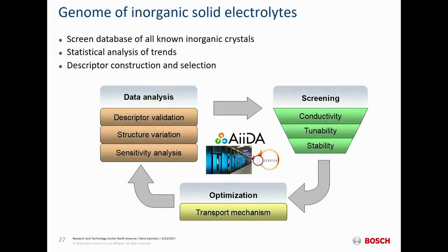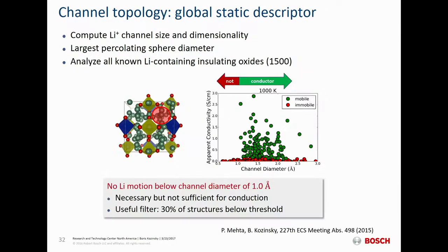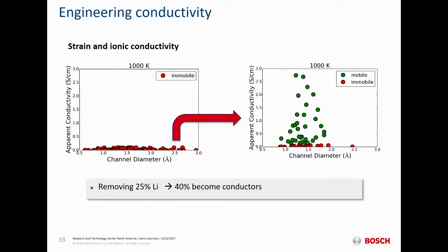And taking this further into screening for better materials, looking at all possible oxides that exist that contain lithium, we started looking, essentially in an automated way, using ab initio molecular dynamics in hundreds of these oxide compositions. I'll just jump to the summary of the result here. We did find in many, many crystal structures that you pull out from the ICSD database, when you start running molecular dynamics, things don't move, exactly because you already have an ordered structure ahead of time, right?